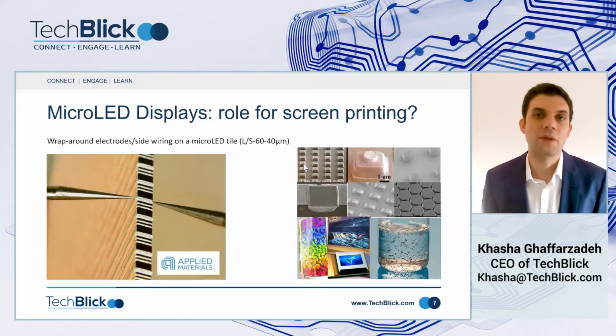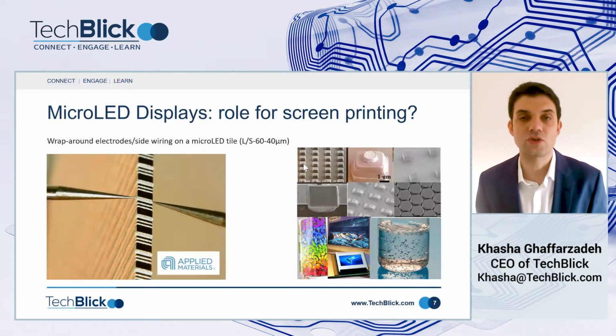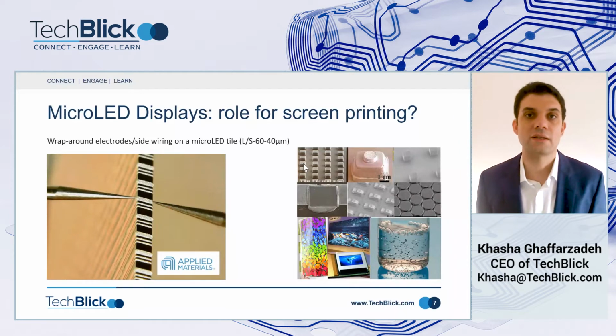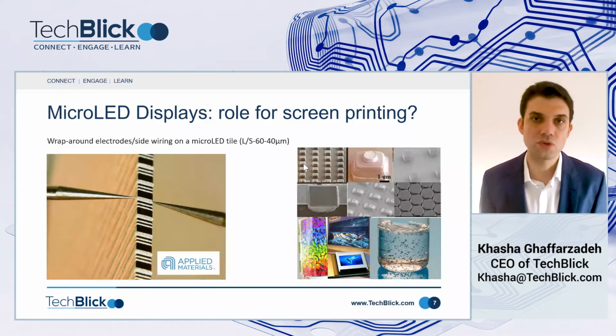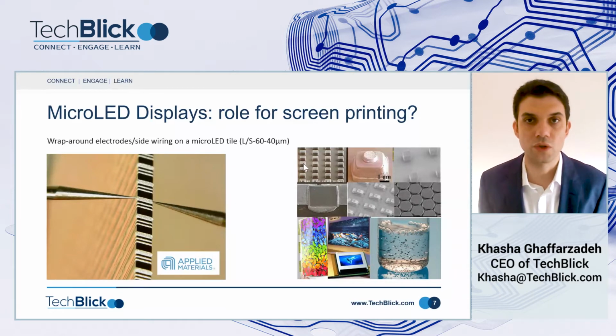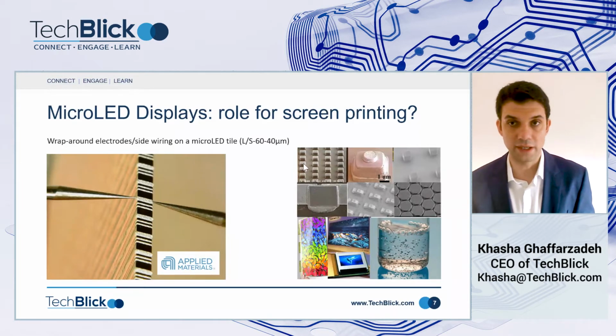And this is an example by Applied Materials. This comes out of their Italy group. And what you can see is that they are screen printing electrodes that wrap around the edge of the glass, connecting the front to the back side, and they're achieving a line width to spacing ratio of around 60 to 40 micrometers. And clearly the advantage here is that you don't need vias and you're doing additive printing. So I think a very interesting approach, and this is an engineering problem that is not, let's say, as sexy as the transfer problem, so it receives less attention, but it's equally important, and I think printing can play an interesting role here.